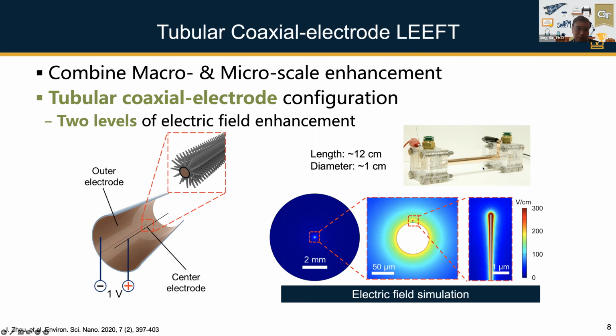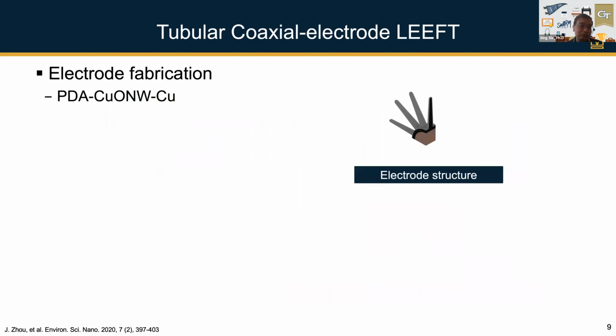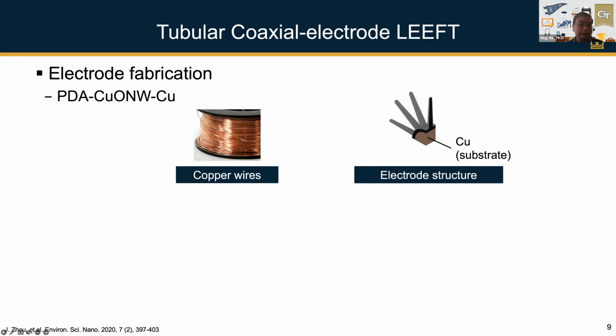So you have the copper electrode outside. The key component, the active component, is really the center electrode. For the center electrode, what we're using now is a polydopamine coated copper oxide nanowire modified copper. Let me get into some details to explain what it actually is. We start with a copper wire. This is a commercially available copper wire, and it's actually pretty cheap. For this 1 mile long copper wire roll, it costs less than $10.